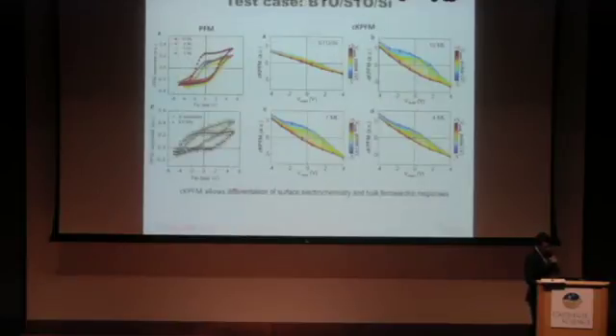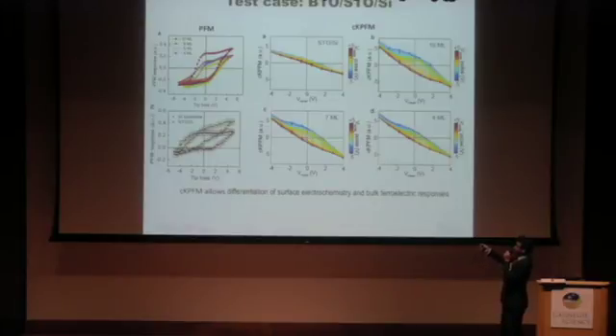So we wanted to see if we could measure this kind of dispersion in the polarization in the ferroelectric states. To do so, we were very lucky to collaborate with Catherine Dubourdieu, who is now in Berlin. She grew some barium titanate on silicon, and we did these CKPFM studies. This STO on silicon, you can see it's pretty much flat. There's hardly any dispersion. In the 10 monolayer case, you can see one polarization state here and another polarization state here, and the width reduces as you make your barium titanate thinner. So this is the 10 monolayer case, 7 monolayer case, and 4 monolayer case. But still, you can see that there's a switchable polarization at 0 volts.